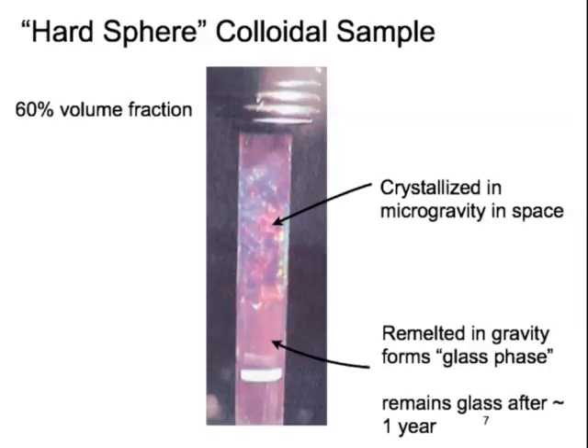So in order to make these samples, you take the plexiglass spheres, and if you really want to be able to see into them or do scattering from them, you don't want them to have a big contrast with the fluid that they're in. You also don't want them to van der Waals attract. Van der Waals interaction is fluctuations in the electromagnetic field, right? And it's completely quantum mechanical. But the way you can get rid of it is if the dielectric constant of the medium that you're in is exactly the same as the dielectric constant of your spheres, there's no van der Waals interaction. It's the same medium, right?